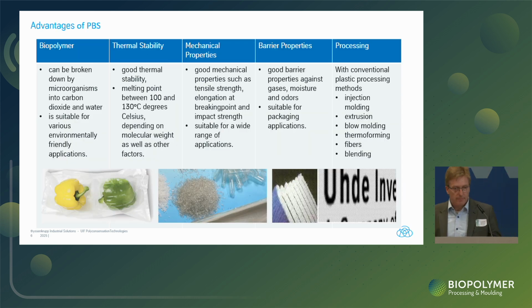So now this is getting a little bit tricky because I cannot read it completely. What do we see as advantages of PBS? First of all, PBS, I said it's a biopolymer. This means it can be broken down by microorganisms to monomeric units and can be degraded completely. So this makes it suitable for many environmentally friendly applications where biodegradability is a must. On the other hand, we see the good thermal stability of PBS. It has a melting point of about 115 degrees, which makes it a good choice for many applications where good thermal stability is required, but not too high.